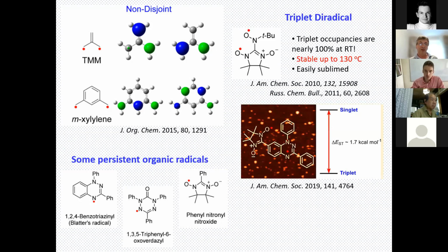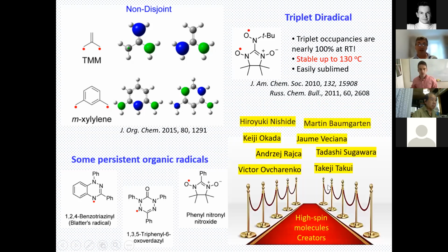They published a very famous work in which they described triplet diradicals with a high energy gap between the triplet ground state and the excited singlet state. They are stable up to more than 100 degrees Celsius. They can even be sublimed and deposited via vapor on some surfaces. And now we can open the so-called red carpet of high-spin molecule creators who succeeded in the synthesis of many triplet diradicals. They are very stable and very useful for future application.